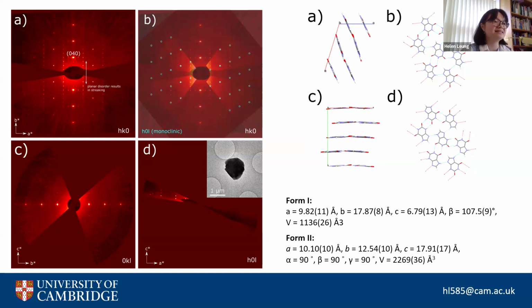And actually what was very interesting is the structure solution of the orthorhombic Form 2 structure came from a bicrystal where we could see two reciprocal lattices in that space, and we had to separate those reciprocal lattices and then run them both through structure solution. And it was revealed that one of the reciprocal lattices corresponded to Form 1 xanthine, and the other corresponded to Form 2 xanthine. So in other words, both Forms 1 and 2 were present in the same xanthine particle, which was like a bicrystal.